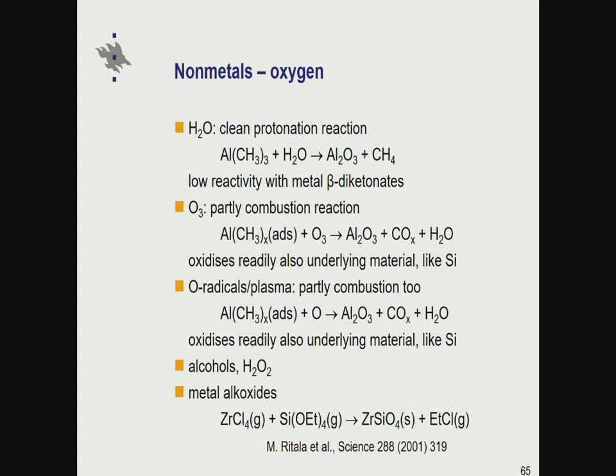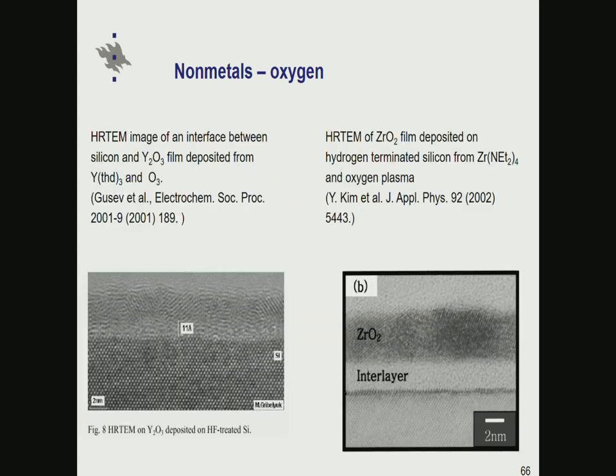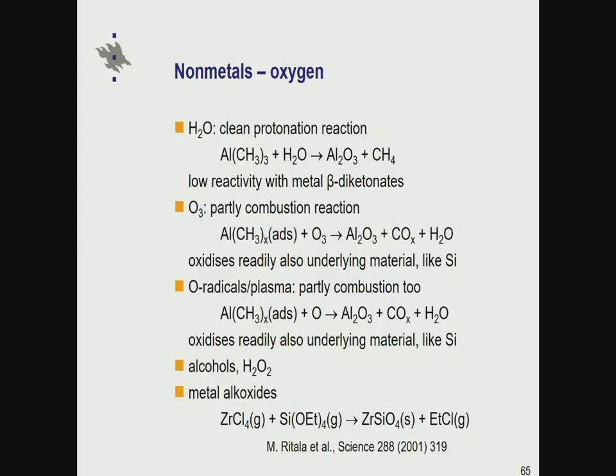Alcohols, hydrogen peroxides have been used to some extent. We came up with the idea of using metal alkoxides as oxygen precursors at some point, for this same reason. Our thinking was that in this case oxygen is already bonded very strongly to silicon, and as a result it's not available to oxidize the substrate surface. And indeed, it seems to be working pretty nicely.